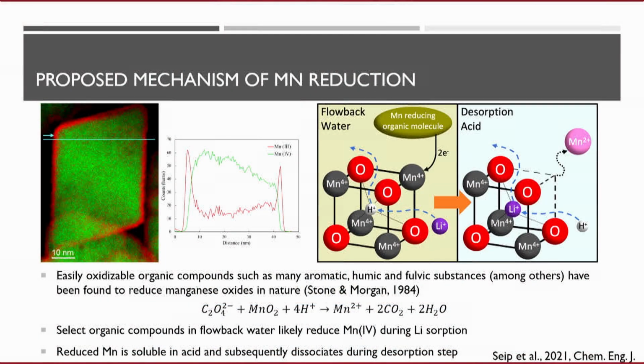So when we analyze this a little bit further, you can see there's a mineral on the left-hand side. We're using electron microscopy with a technique called EELS that can actually map what's called the valence state of the manganese. The green on the inside is manganese 4, which is the most oxidized form of manganese, and we make the mineral out of this. And the good thing is it's not soluble; manganese 4 is very insoluble in water.